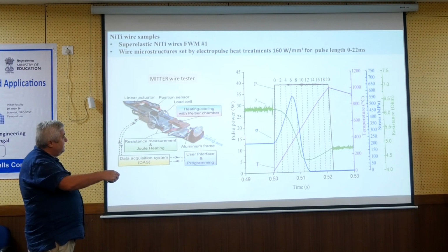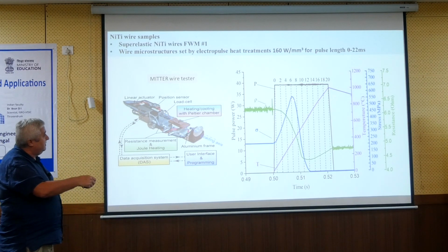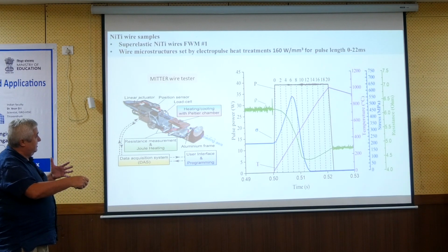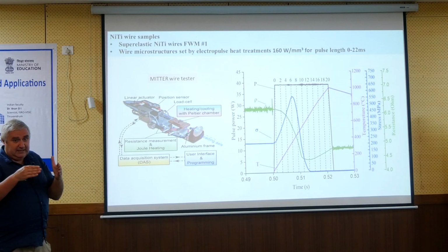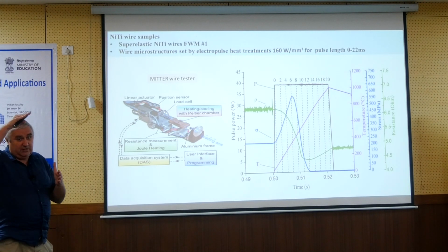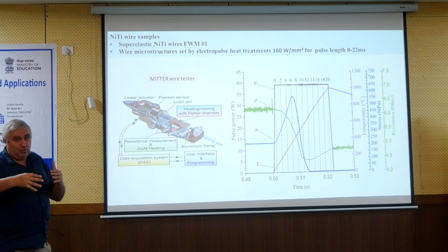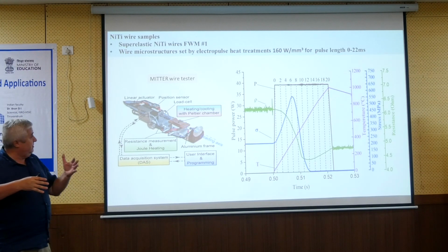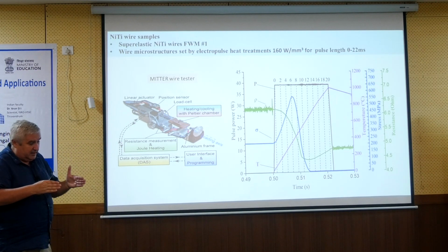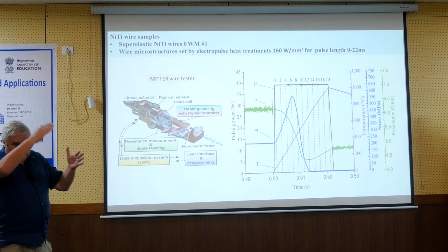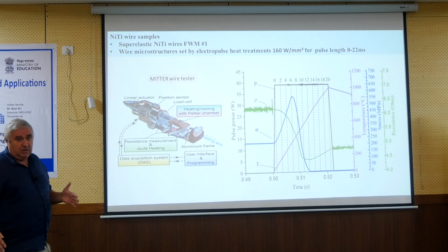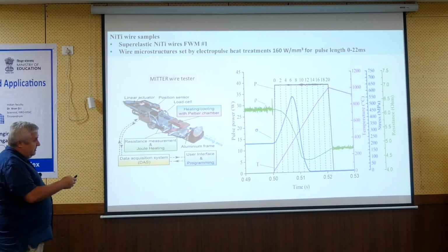But at some moment, the martensite starts to deform plastically. So when the martensite deforms plastically, the increase of the stress will stop. The wire is transformed to austenite, and then the thermal expansion occurs, and the stress goes down to 0. You know?